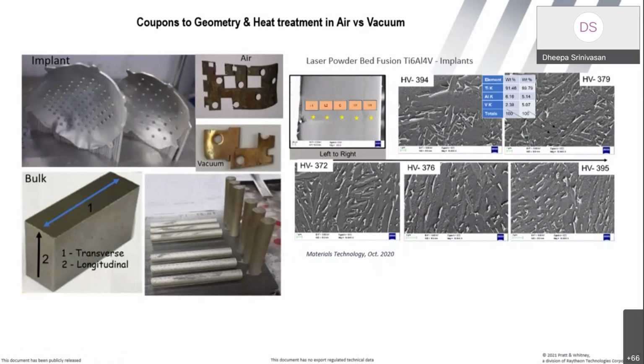Where typical Ti-6-4 heat treatment, stress relieving heat treatment, involves heating in vacuum. Now, in the interest of urgency, for example, an implant like this is typically given to a trauma case. In this particular case, I think it was a head injury or something like that. So immediately the doctor wanted the cranial implant. We made it overnight by taking the DICOM image from the CT scan that the doctor had sent. However, you need to heat treat in vacuum, and that does take time if you don't have a vacuum heat treatment right next door.